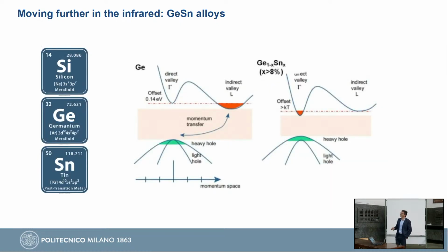So we go down one step in the periodic table, and we find tin. Tin at room temperature is essentially a metal with a tetragonal phase. If you cool it down a bit, it becomes a diamond-like structure, similar to germanium. And so we can think about mixing these two materials and going from a material like this, which is germanium, an indirect material, so very little absorbing, to a material like this, which is direct and has a smaller band gap.